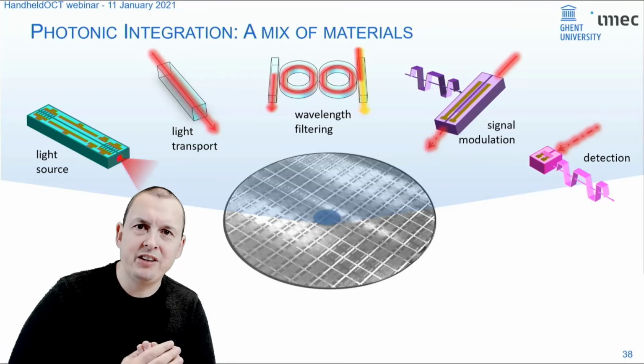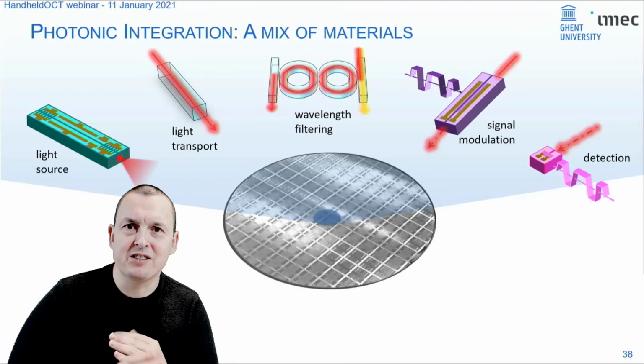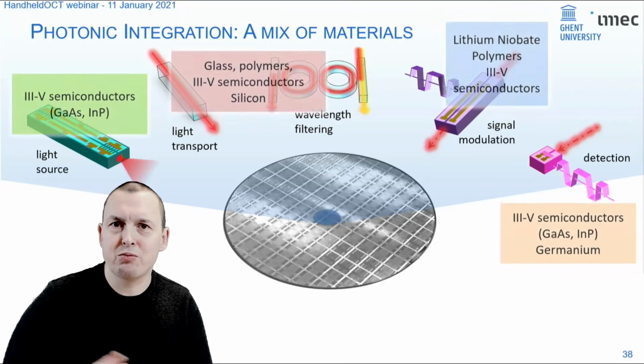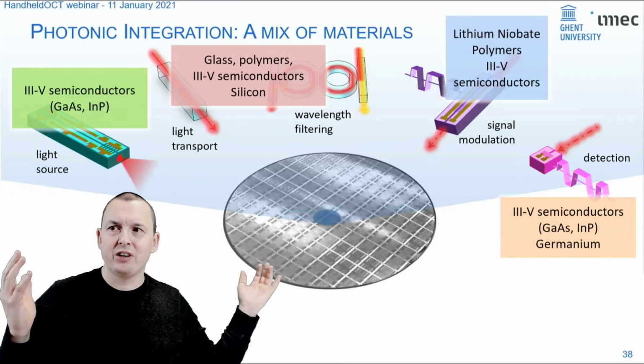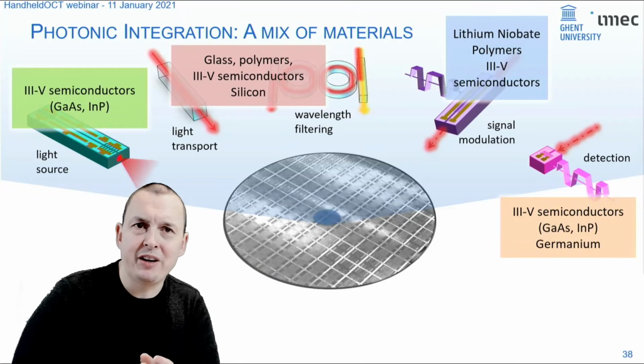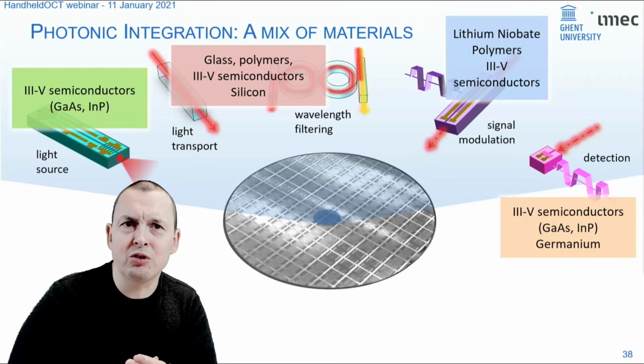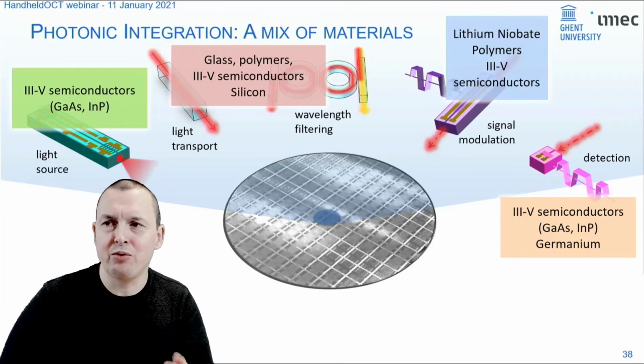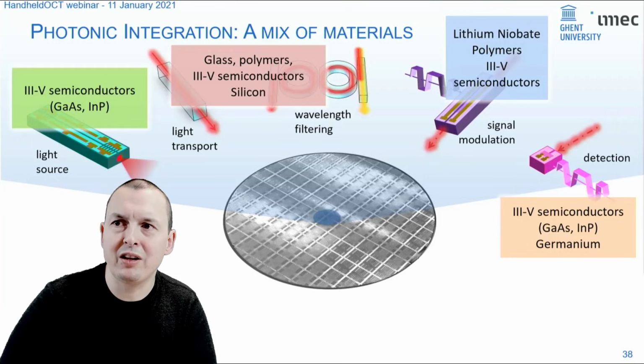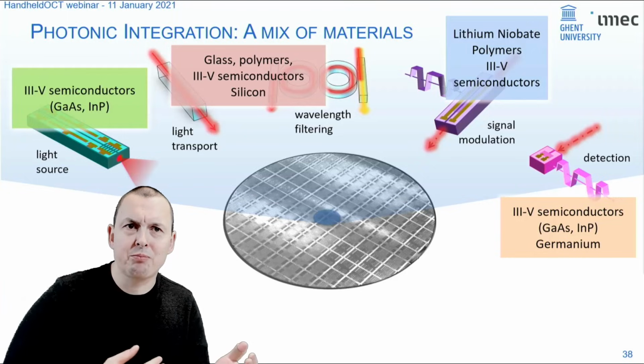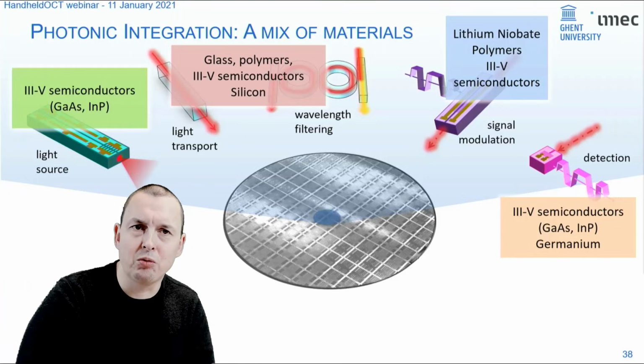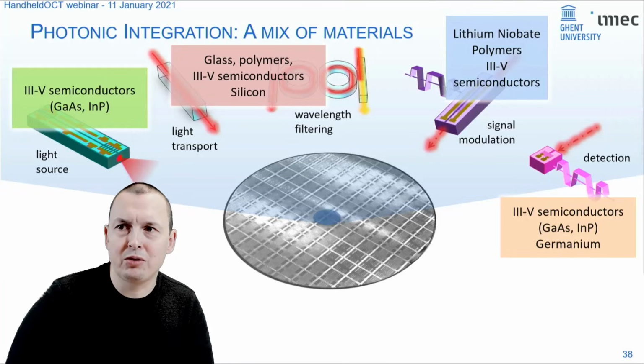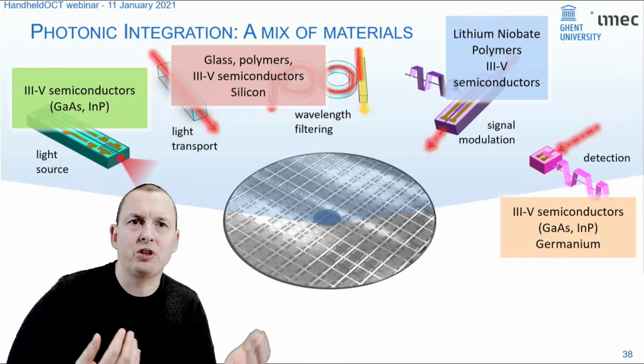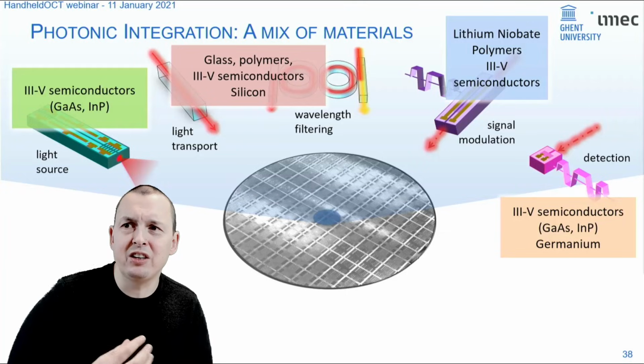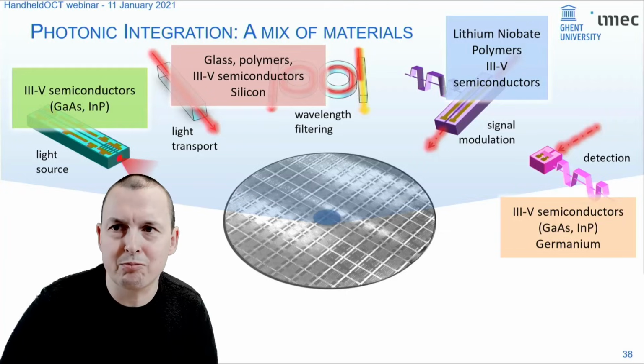Unlike in electronics, where 99.9% of the electronics is all made in silicon, in photonic integrated circuits we see a really wide variety of materials. For instance, if we want to make a laser or a light source, we almost always end up with III-V semiconductors, because these have a direct band gap that is really good at emitting light. While if we want to guide light, we want preferably a material with low loss. And so we end up with glasses or polymers. III-V semiconductors work, and silicon works, but they're not as good and low loss as, for instance, glass and polymers.